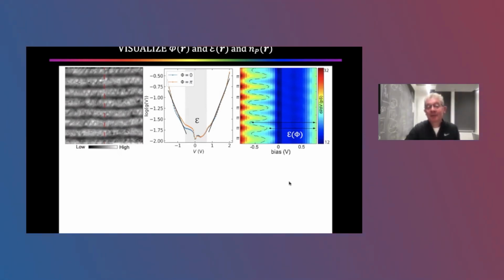If you measure the differential conductance plus minus several volts along the red dashed line, and I plot the differential conductance as a color scale here versus energy along that line, what you see is that the energy difference between the top of the lower band and the bottom of the upper band is modulating. And it's modulating once per supermodulation period. And it's modulating by a lot. So we were thrilled to see that.